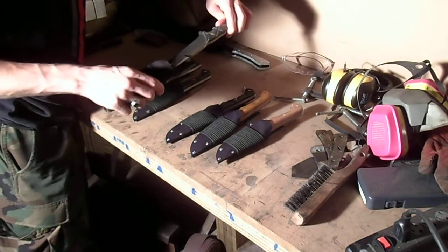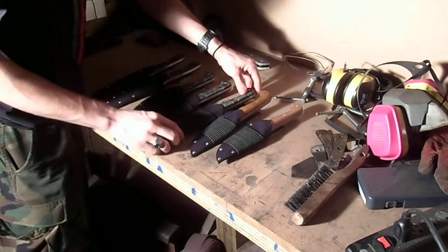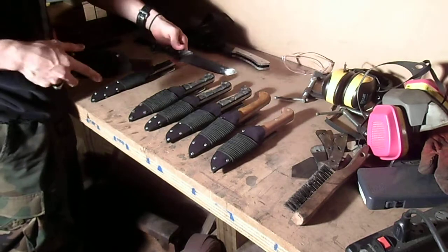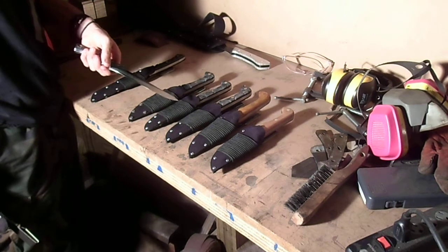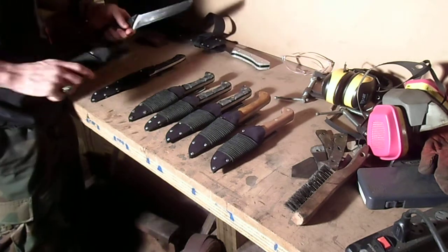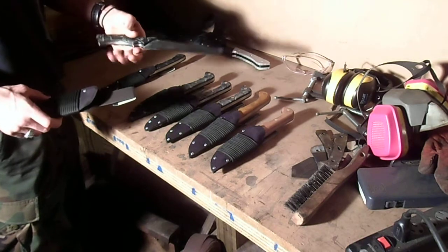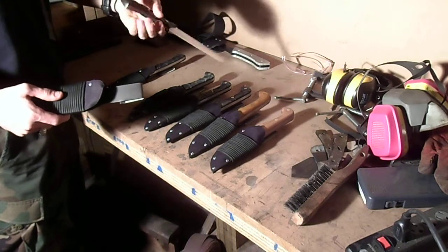These three are pretty similar to one another, and this one's the Mead Wolf utility knife. They're all quarter-inch 5160 steel, heat treated to between 55 and 60 on the Rockwell C scale — probably around 57-58 for most of them. These two I'm not as sure about since I did them at home without a Rockwell tester, but probably similar hardness. This one is 12 inches long, and these are 10, with a Scandinavian ground edge as usual.